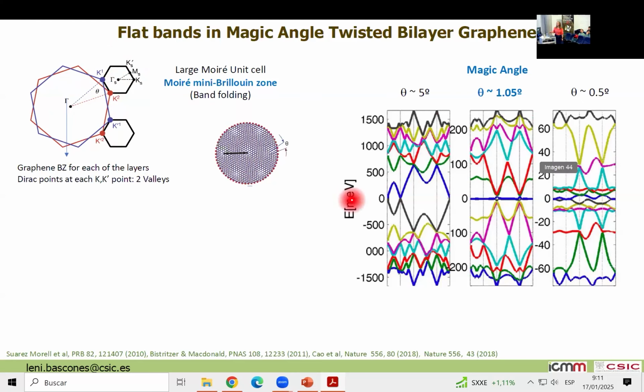I'm going to focus on the bands that are close to the Fermi level, to the chemical potential, and you can see how when you change the angle, around 1.0 degrees in this case, there is this very, very flat band. This is what is going to interest us, because people said, okay, this system has to be interesting. What they saw in this paper is that there is not just one angle at which the bands become so flat; this is just the largest angle, but there are several other angles at which this also happens.